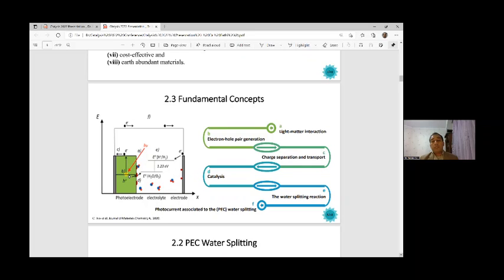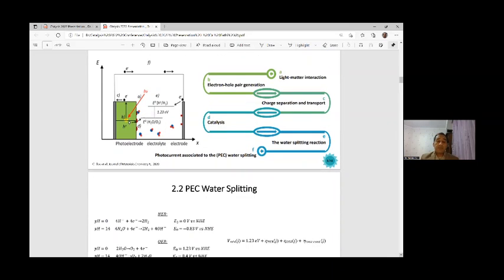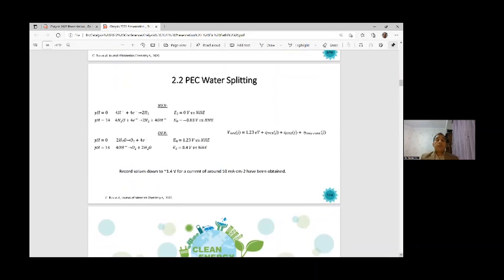In the continuation, we have the water splitting reaction towards the whole and final performance of the system. Here, you can see two important reactions, the hydrogen evolution reaction and the oxygen evolution reaction. At the right, this relation tells us the minimum junction voltage required to have a high performance for the system, according to what was mentioned above.